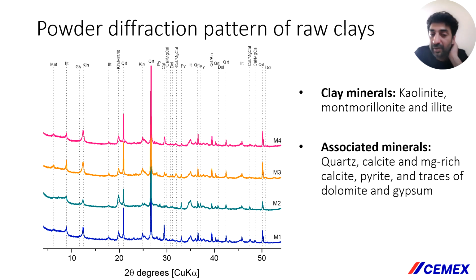Okay, so we carried out XRD of the rock layers to identify the minerals present and the associated minerals present. And apologies, we couldn't get hold of one of the samples in time, which basically meant the diffractometer eventually got really busy and outbooked, and so raw clay M5 is missing from this data set. But broadly, the 4 raw clay samples displayed here showed similar mineral makeup, with kaolinite, montmorillonite, and illite as the clay minerals. And the associated minerals identified were quartz, calcite, pyrite, traces of dolomite, and gypsum.